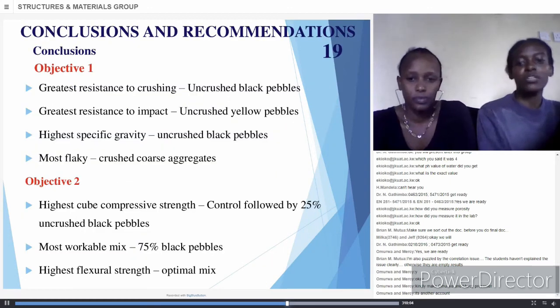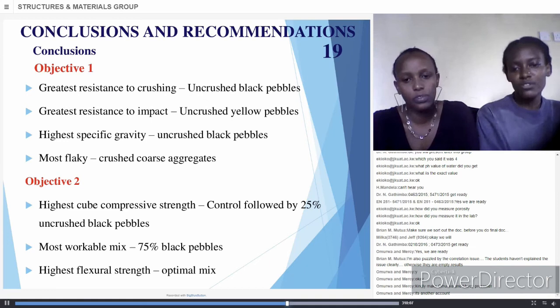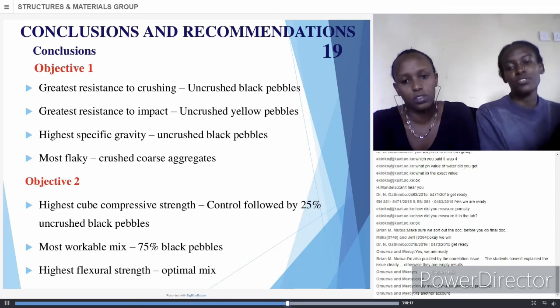Conclusions and recommendations. From our first objective, we were comparing the properties. We found that the material with the greatest resistance to crushing was the uncrushed black pebbles. The greatest resistance to impact was the uncrushed yellow pebbles. The highest specific gravity was the uncrushed black pebbles, and the most flaky was the crushed coarse aggregates.